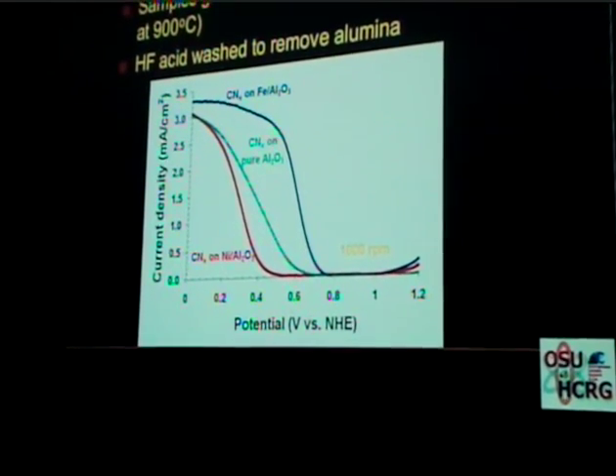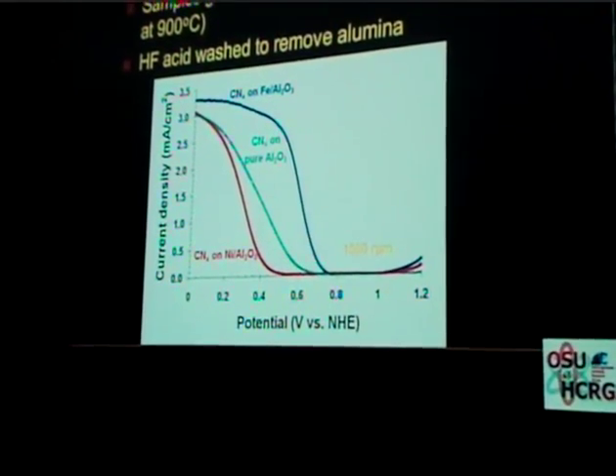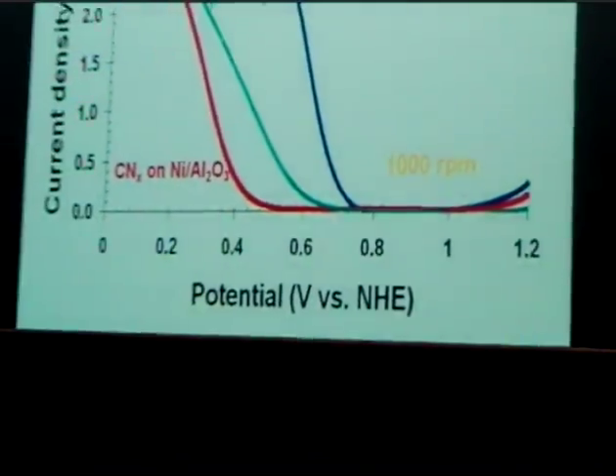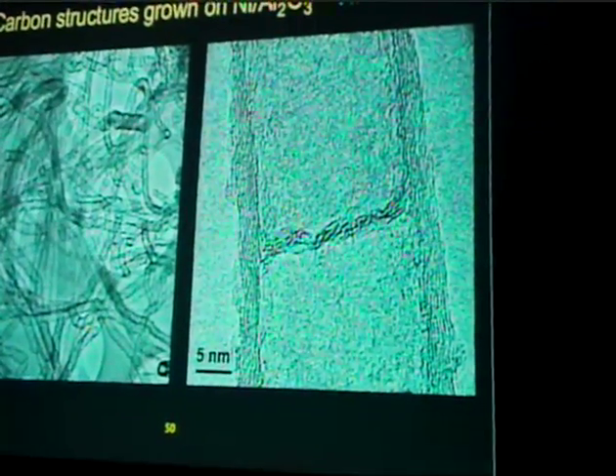So clearly we're getting significant activity, and again, if the starting material has iron to start with, we get better activity. And if we look at the TEM images, these are carbon structures grown on nickel-containing alumina.